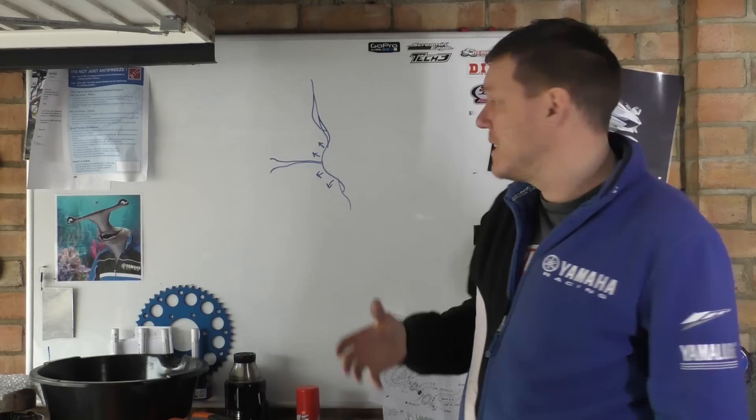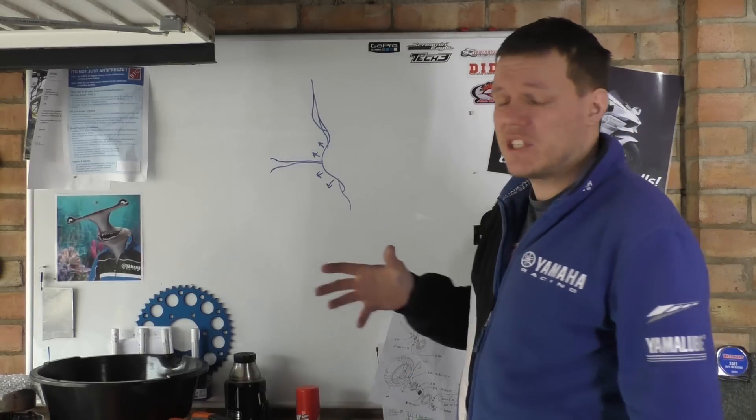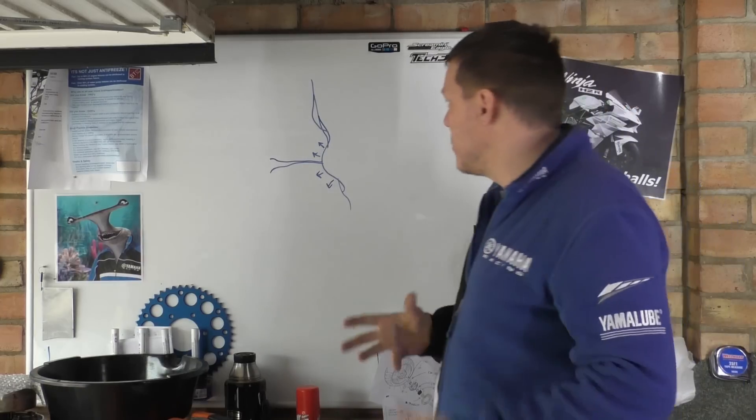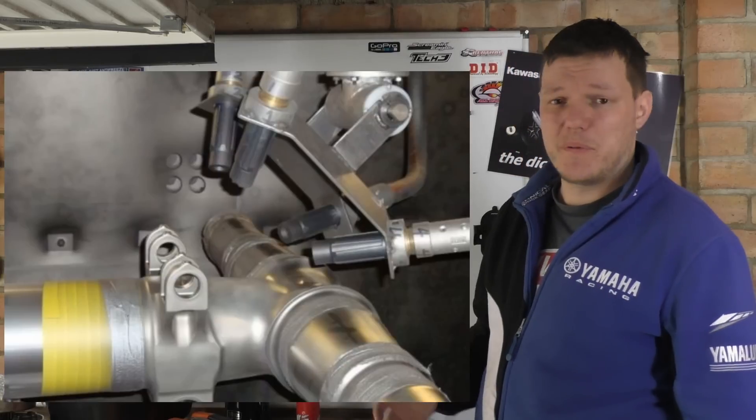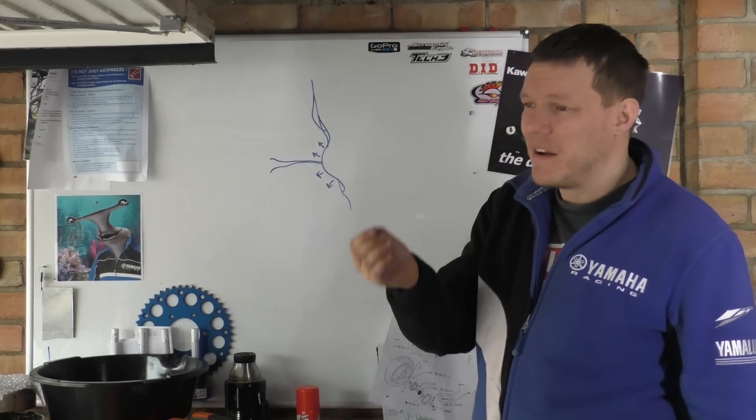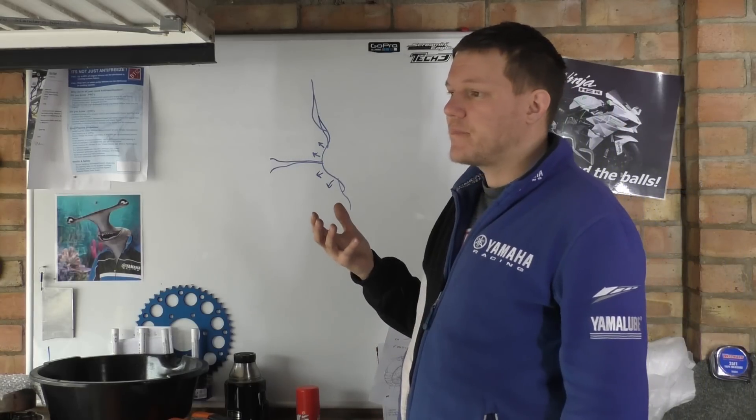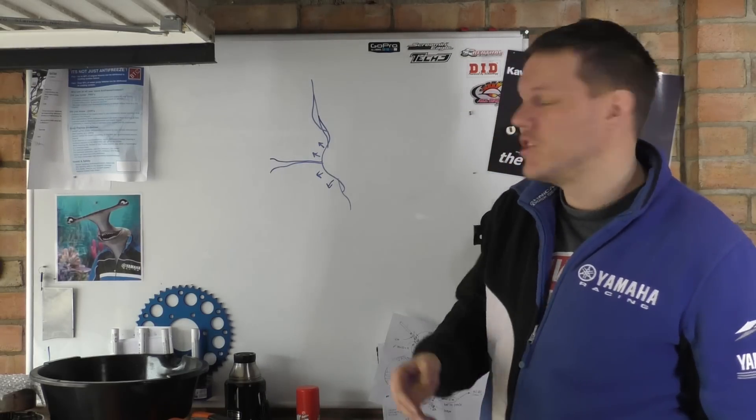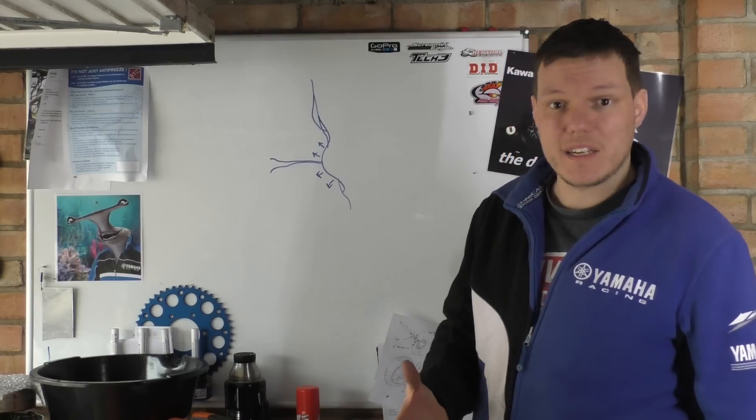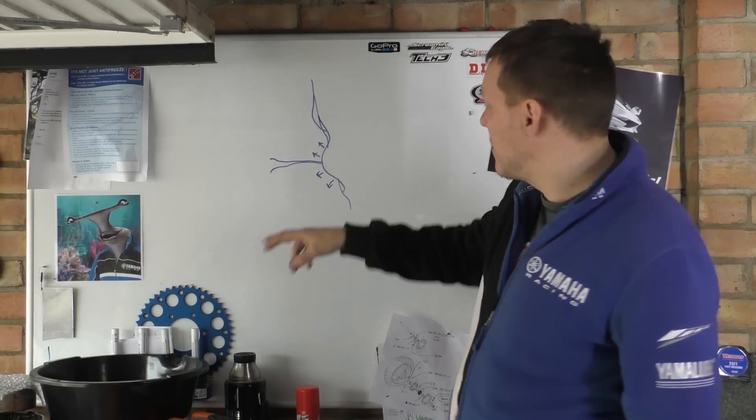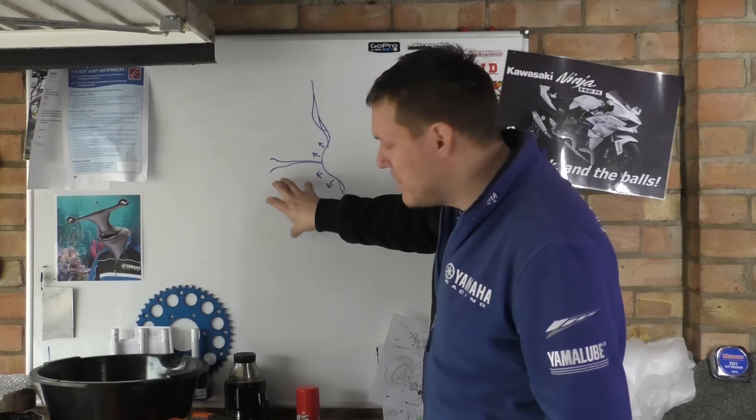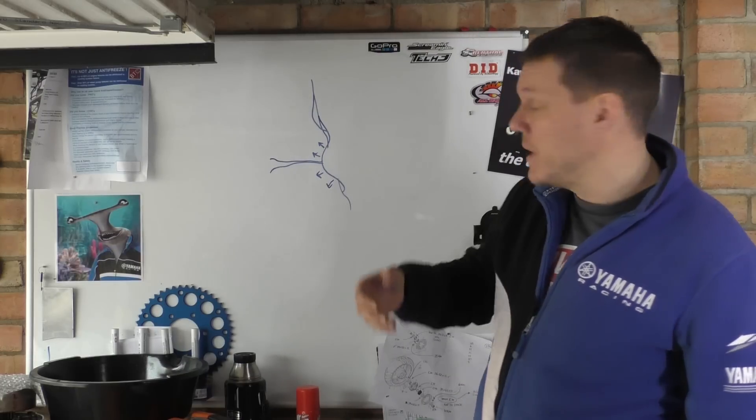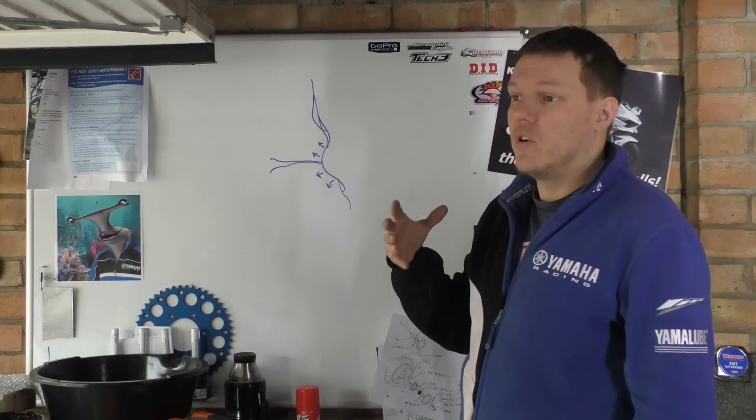Basically it's like sandblasting. Sandblasting is obviously an abrasion. This is actually trying to plastically deform stuff. It's not trying to scrape away stuff. Yeah, it's literally like a mini hammer just giving it thousands of taps all over. And like I say, it's like a sandblaster apart from it's got a lot more pressure and it's got a lot more oomph to speed up these little ball bearings. The little ball bearings are absolutely tiny. So it's to induce surface hardening-ish. Surface hardening is not its intention, its intention is to relieve these stresses to stop cracks and fissures from opening, because all cracks start with a micro crack between a grain boundary. If you keep on putting stress on these things, cyclic stresses, fatigue basically, these things will eventually crack and that's where they'll break.